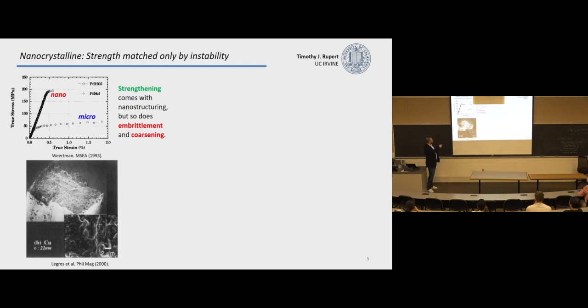You can see this on this top left plot. This is a stress strain curve, a really old one of the first ones from nanocrystalline palladium and microcrystalline palladium. And here you can see your strength has gone from 40 megapascals to a little under 200. So you get a huge increase in your strength, a 5x increase in your strength. But the sample fails much earlier. Rather than elongating out and stretching quite a bit, you fail early in this tensile type of deformation.